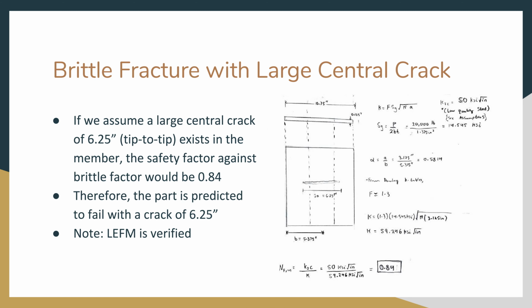Our analysis of brittle fracture will be based on the assumption of poor quality control. As such, the C-channel making up the H-frame will be assumed to have a 6.25-inch crack spanning its middle section, and this geometry will be simplified to that of a rectangular cross-section for use of the Dowling tables. The K1C value is based on an average of multiple steels and then lowered slightly for the assumption that they're using the lowest quality steel possible, as they're likely saving money on the bill of materials here. Completing this analysis, the safety factor is found to be 0.84, which indicates failure via brittle crack propagation. It should be noted that the LEFM is verified here, as is visible in Table A2.